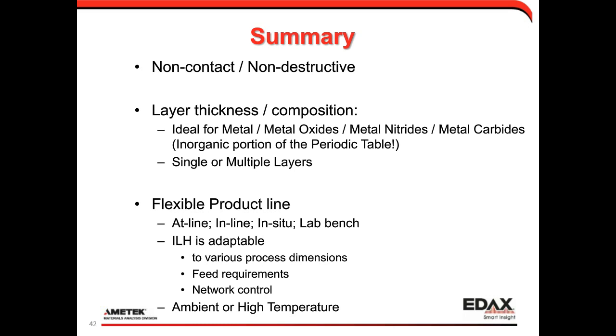There was another question here. Can you use XRF to measure the intermetallic layers that form between two metal layers? This is more difficult for XRF to measure. If I understand this correctly, you put down two metal layers, and in the process of doing that, you form some sort of very thin alloy region between the two layers. What happens in this case is we're getting signal from both of those metallic layers, and we're getting the value of mass coverage for each of those. And there's no unique signal associated with the intermetallic layer. So it's difficult to assign any signal to the intermetallic layer, which makes it a situation where it's more difficult for XRF to make a measurement.